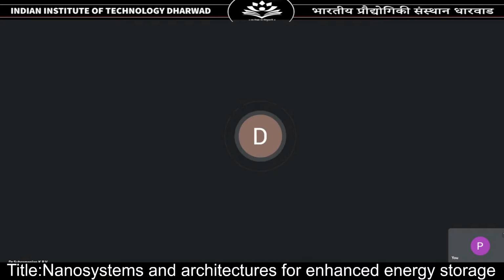Okay, fine, yeah. So coming to the polypyrrole, polypyrrole is a conducting polymer. There is something called electropolymerization. Now, polypyrrole can be formed in two ways. One is chemical polymerization, and the other one is electropolymerization. If you do chemical polymerization, you take pyrrole, which is the monomer, then add a polymerizing agent, and then it becomes polypyrrole. The other way is you take a pyrrole solution and do electropolymerization, which means you apply a voltage in a suitable solvent, and then the polymer fibrils grow naturally. So that is how we were able to get those nanofibrils of the polypyrrole.